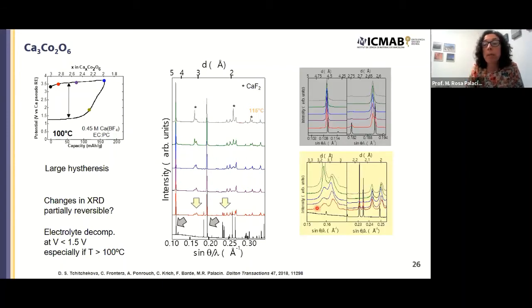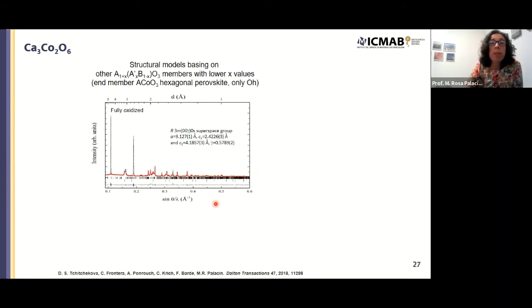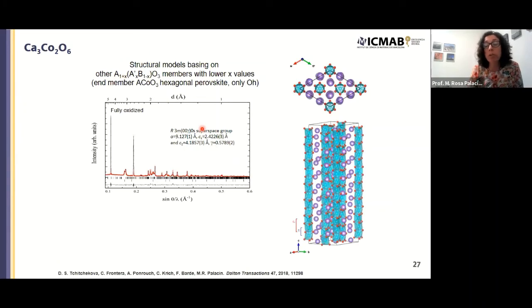Because we see that in some regions the pattern changed a lot, and in some other regions peaks remain almost unaltered. And we were able to find a model for the crystal structure of the oxidized compound, looking at other members of the same family of compounds. And this has an incommensurate crystal structure with two periodicities for the C, with two C-axes, one showing the cobalt periodicity and one showing the calcium periodicity.